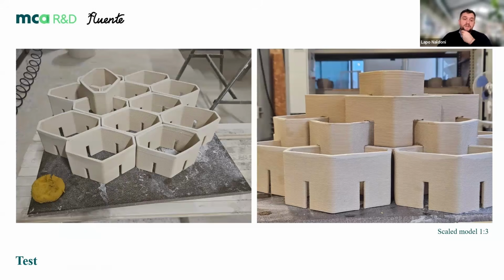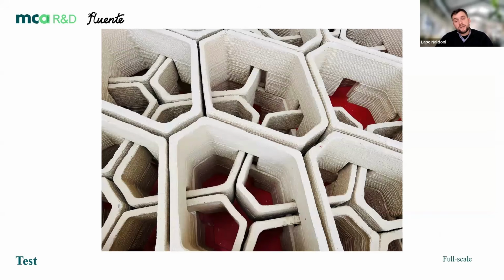Why ceramic? Because it's really strong and it is really fast, and it is a material from the past that you can reuse an infinite number of times. So in a blink of an eye, we designed these blocks in 3D, and we produced with Fluente some mock-up tests at 1 to 3, and we redesigned those blocks at full scale, and we tested with stoneware, with recycled stoneware. We tested the system. So we print with raw clay, and we fire this clay inside the kiln at around 1200 degrees Celsius, and we obtain these really strong blocks.